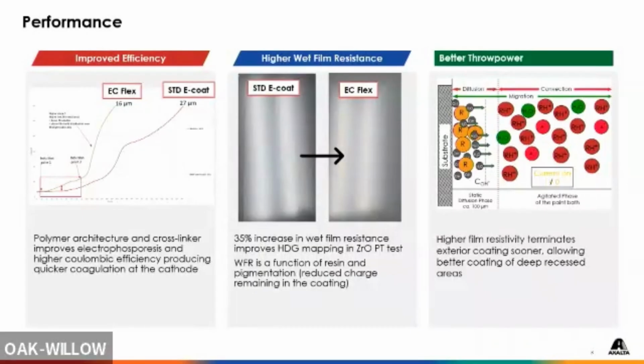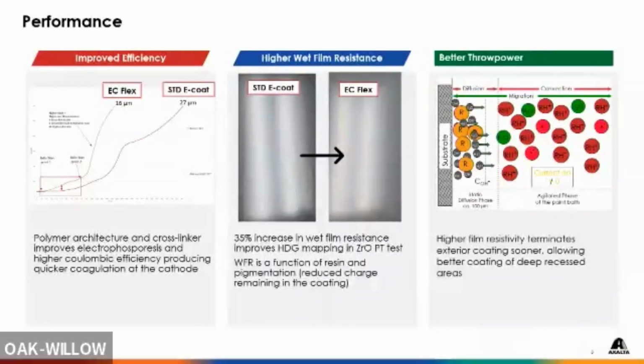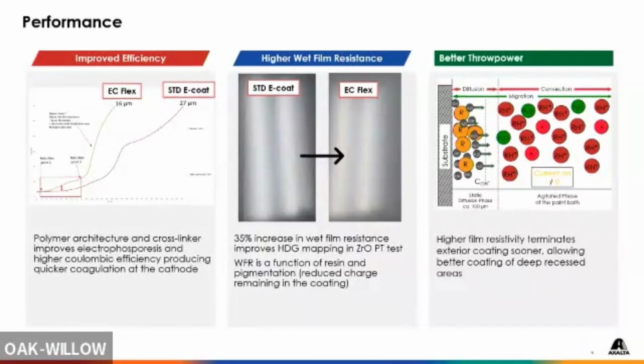And then finally on the right, again, we talked about coagulation. You can see here, this is just a cartoon that shows, on the right is my Ecoat bath, on the left is the actual deposition process happening, and my resin particles are coagulating in that hydroxy boundary layer. Again, the ability to get to that point and the coagulation of that point is what we're trying to improve, and we did. So we were able to improve throw power, wet film resistance, and efficiency as part of this new development.